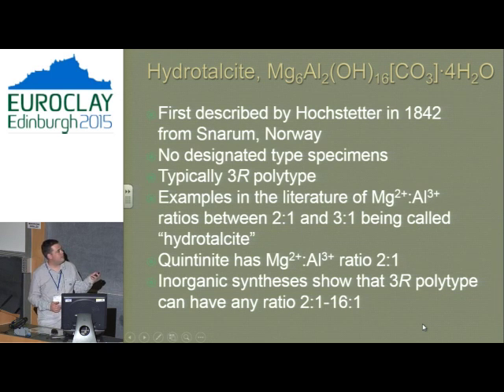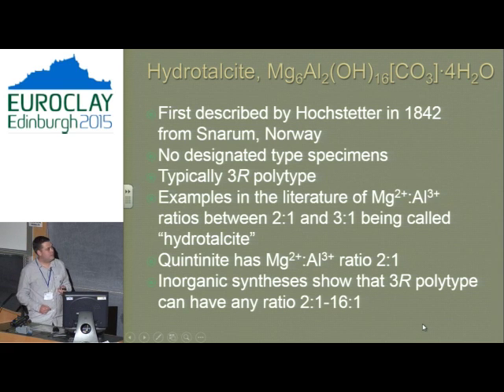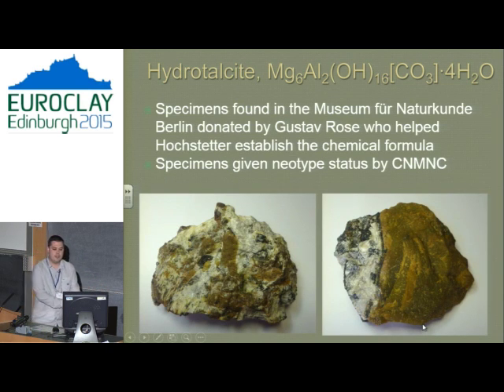And in 1993, the mineral called quintinite was described from single crystals in Quebec with a ratio of 2-to-1. From the inorganic chemistry literature, we know that the 3R polytype can persist in any ratio, but in mineralogy, we can't really do much with this. So what we did is a forensic audit of German minerals collections, and we found that these two specimens have survived for 150 years in Berlin.